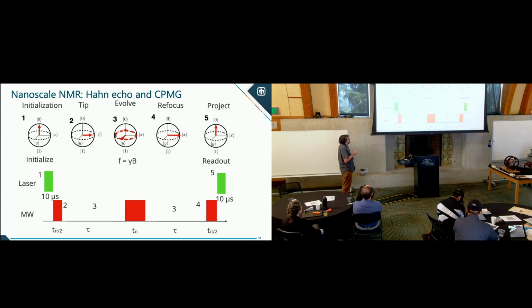Your spins will precess in this XY plane, but they end up decohering because of variations in the local magnetic field. That's T2 star like. This is what's called inhomogeneous broadening. But then if you apply a pi pulse, the spins coalesce back together in their initial position at a time tau of delay. And I'll show you a nice animation of this. In the case of NVs, we have to project it back onto the 0-1 axis to read it out, because we're reading it out optically. But this is a very standard technique within NMR and ESR.